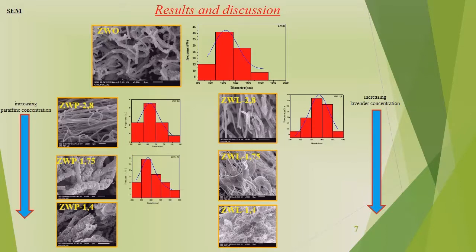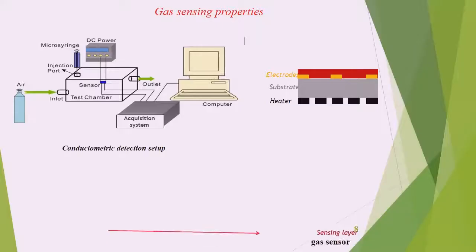The next images display the influence of lavender oil on the tubes. They demonstrate that the texture of the tubes was well maintained and relatively uniform with diameter range of 700 to 800 nanometers. In this part we study the sensing properties of our prepared materials.